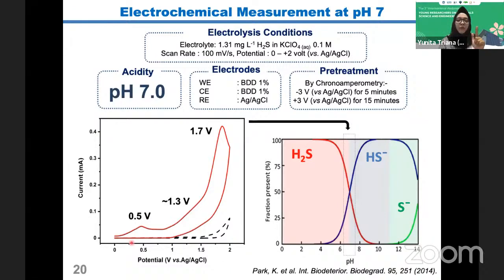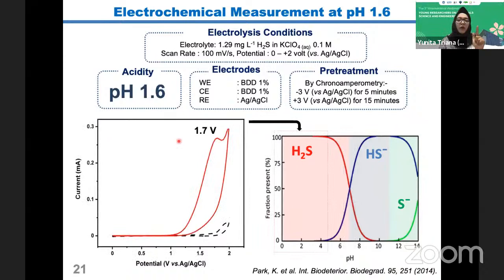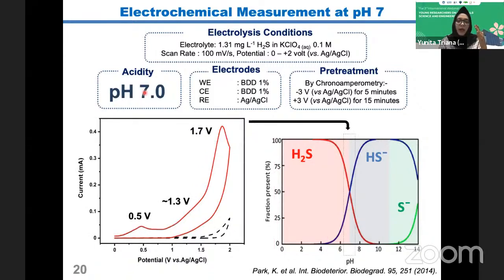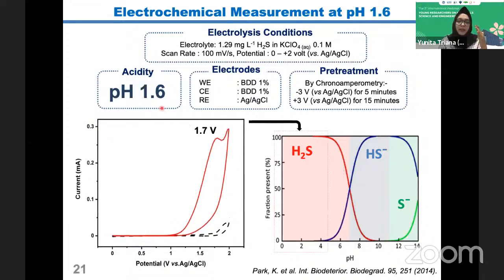And how to confirm the reaction of each signal? So I tried a low pH, pH 1.6. At pH 1.6, I only got 1.74. If you remember, at pH 7 I got three oxidation potentials, and at pH 1.6 I got only 1.74. And based on this graph, at 1.74 there is only one species, H2S gas.